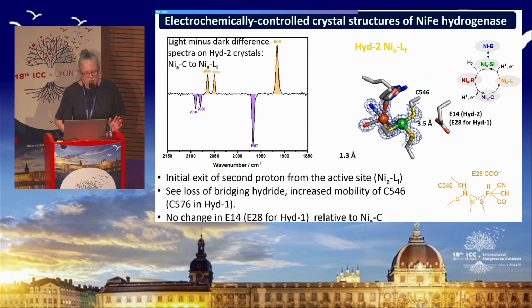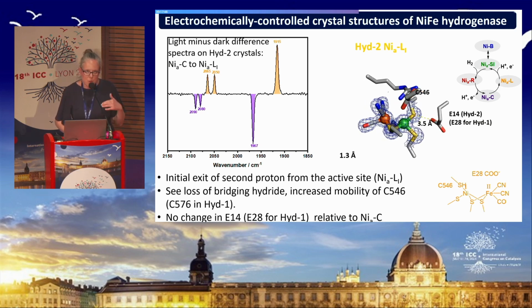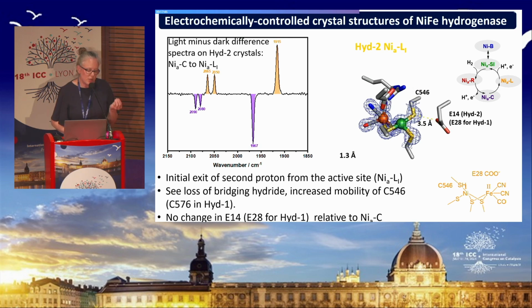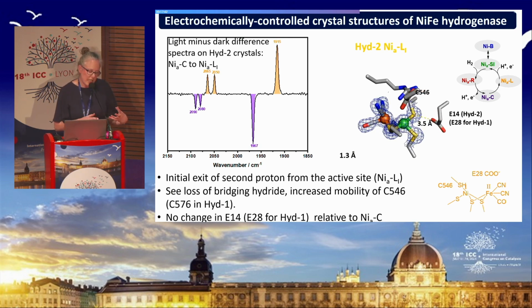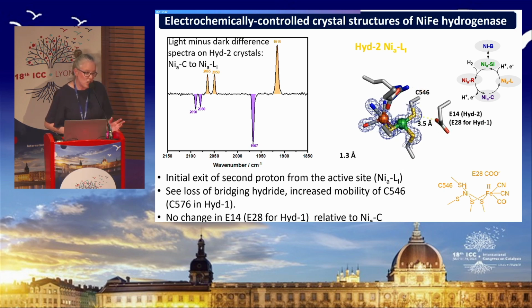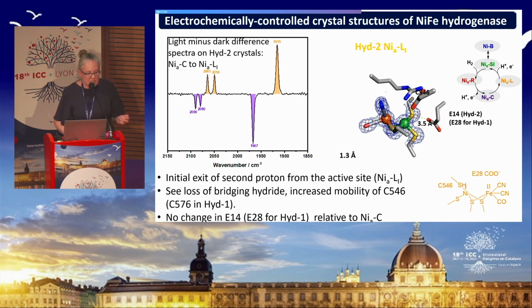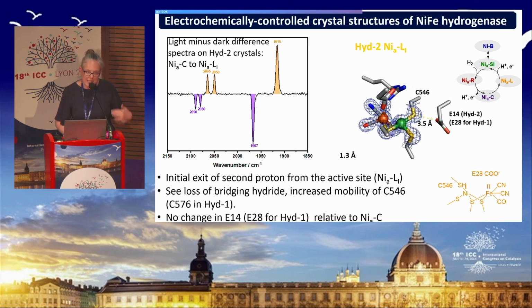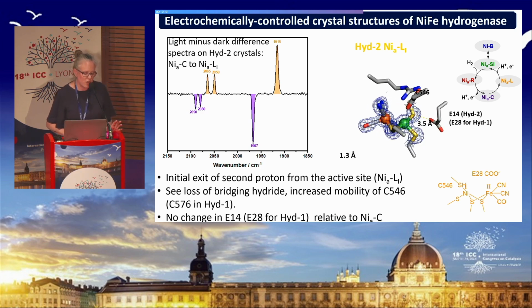So the first thing we've done here is to photolyze crystals in the nickel C state. It's been known for a very long time that the nickel C state is light sensitive, and when you shine light on it at cryogenic temperatures, you can convert it into nickel L. In fact, nickel L was originally thought to be an artifact, and the L comes from L for light. It was thought to be an artifact that you only generated when you shone light on nickel C. Since then, we've shown through catalytic studies under operando conditions that nickel L is actually an intermediate in the catalytic cycle of hydrogenases. And we think that this state that you get from photolysis is the first proton position.